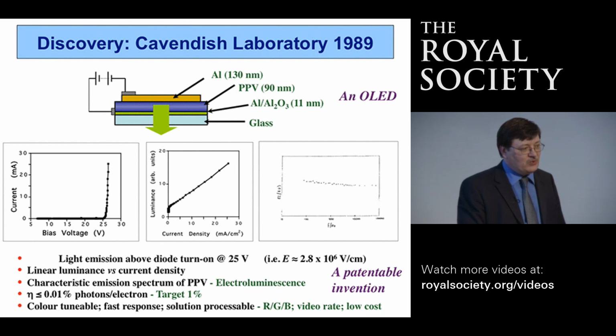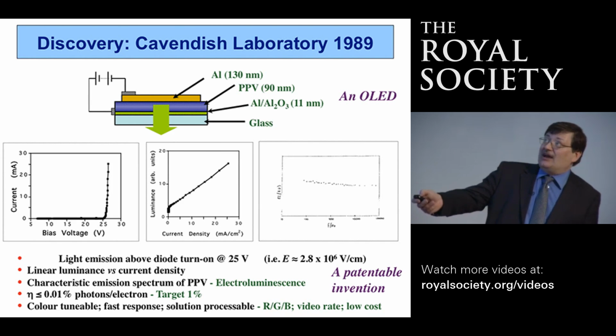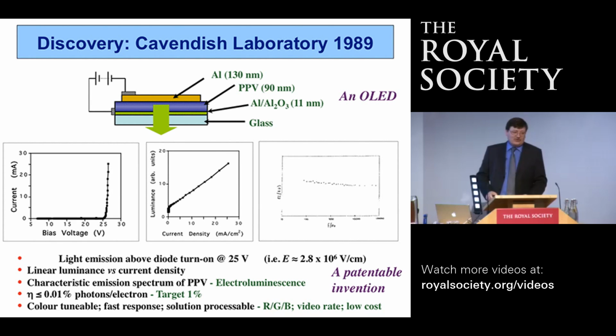It was actually a test sample that was being used to test the dielectric breakdown strength of this layer. And the reason we wanted to know what the dielectric breakdown strength of that layer was that my colleague Jeremy Burroughes was working on field effect transistors, and he wanted to make plastic field effect transistors and wanted a plastic insulator that could be used to provide the dielectric in that structure so that you could apply a gate voltage to the structure and produce a field effect transistor. And I had previously worked on this particular polymer, this PPV polymer, and knew something about it, and we basically decided that it would be an interesting material to test as a dielectric for use in those field effect transistors.